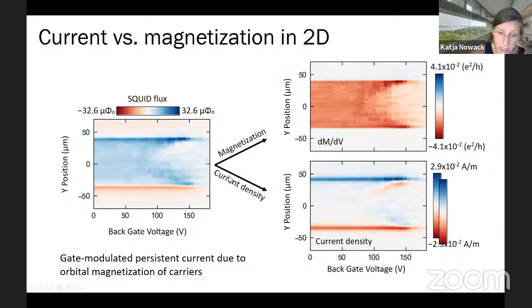That's this reconstruction here. We can also reconstruct from this flux signal a corresponding current density, which is shown here. And so then we would be saying we are modulating the magnetization in the device. If I choose to show current density, I would say we are visualizing how persistent currents flowing in the device get modulated. And I just want to point out the two are really equivalent.